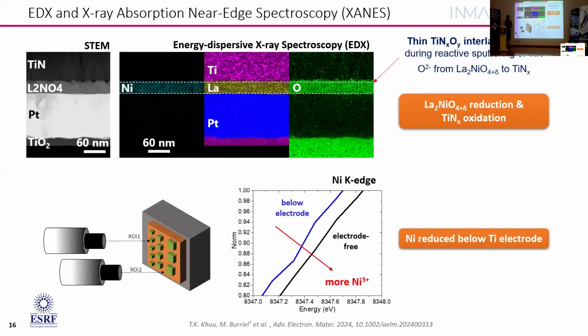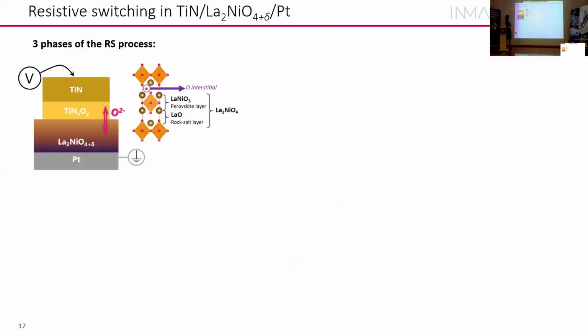We also confirmed this by some synchrotron measurements at the nickel K edge by X-ray absorption near edge spectroscopy. So we measured in the same sample some regions where we had an electrode and some regions where we did not have an electrode. And we see that the nickel K edge shifts. So below the electrode, we have more nickel 2+, let's say, and we have more nickel 3+ in the electrode-free region. So we see that nickel is reduced by the deposition below the titanium electrode.